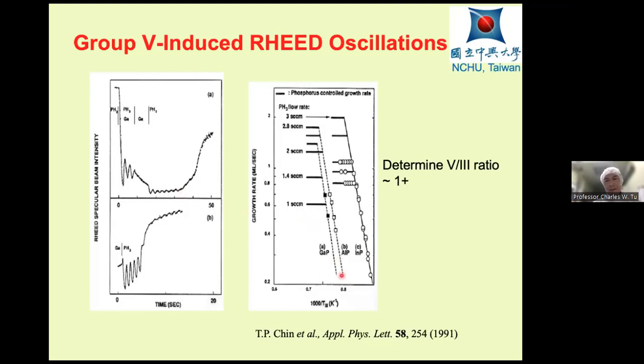Here we can plot growth rate as a function of 1 over the gallium cell temperature. Or here, because I have gallium phosphide, aluminum phosphide, and indium phosphide, 1 over the group 3 cell temperature. As you can see, if I increase the cell temperature, the flux is higher, the growth rate increases, and 1 over T decreases. This growth rate increases until, in this example, the growth rate is limited by the amount of phosphorus, and so the growth rate flattens. This kink here determines the V-to-III incorporation ratio very precisely.